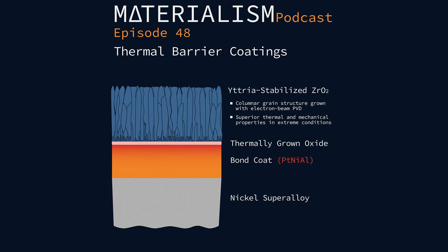So there's been a lot of work where they want to add enough dopants that you get a large number of oxygen vacancies. Because remember, for every yttrium 3+ that you put on a zirconium 4+ site, you create an electron neutrality problem. And the only way that you resolve that is by having half of an oxygen vacancy for every one of those. So in other words, for every two yttriums you put on there, you create one oxygen vacancy. Those oxygen vacancies are great at scattering heat, basically. The phonons that would carry heat through your material get scattered by this.